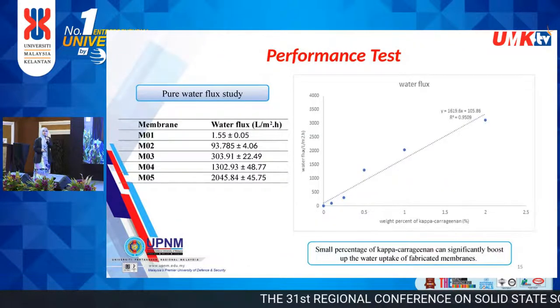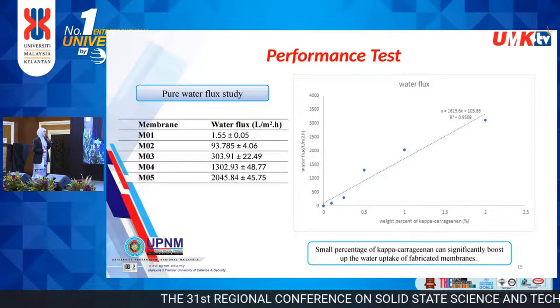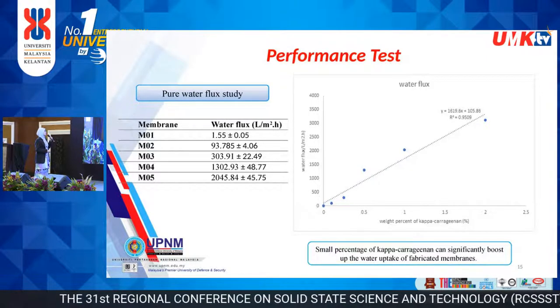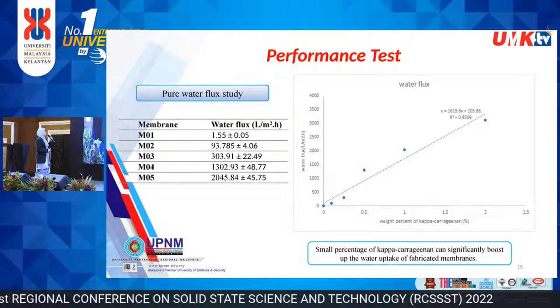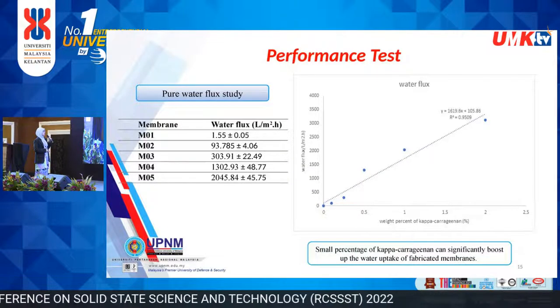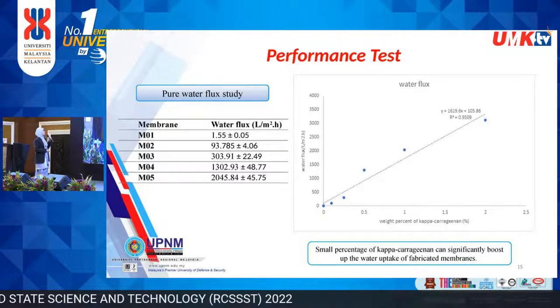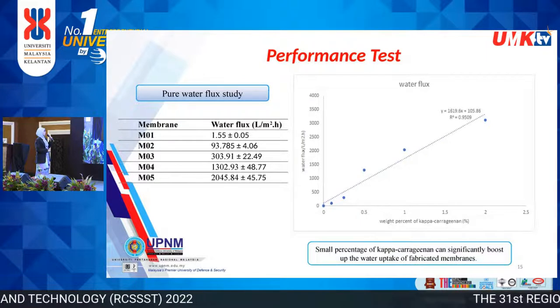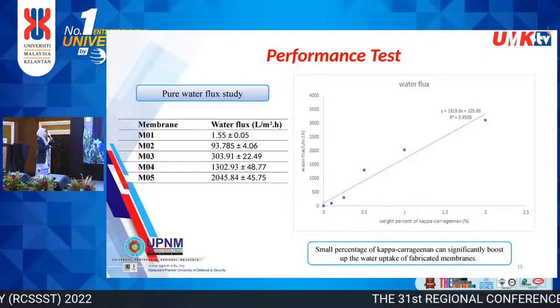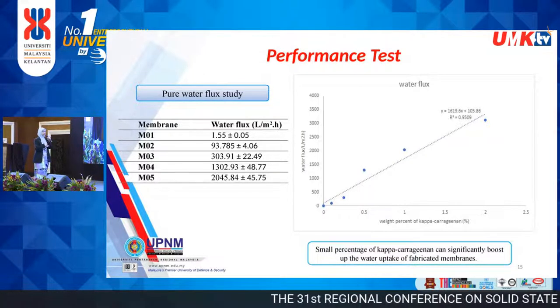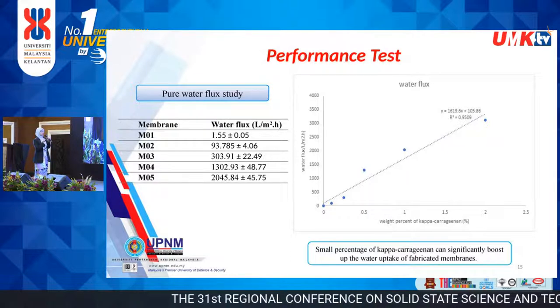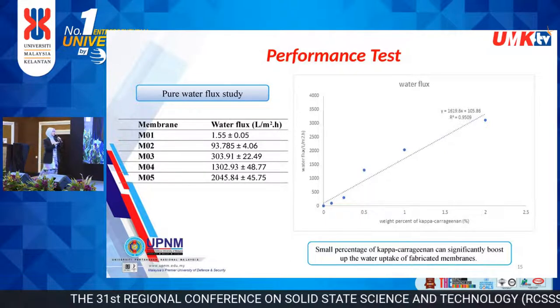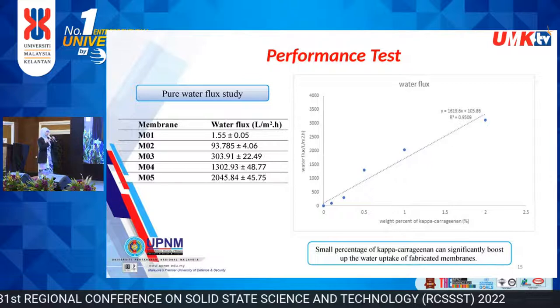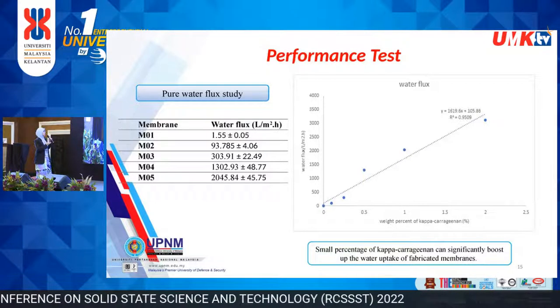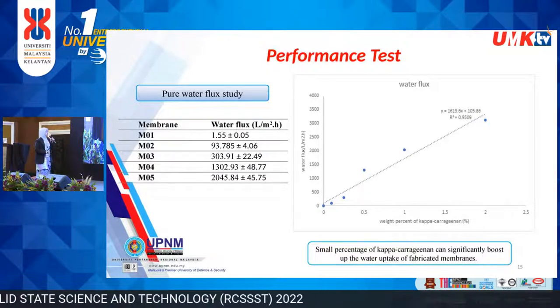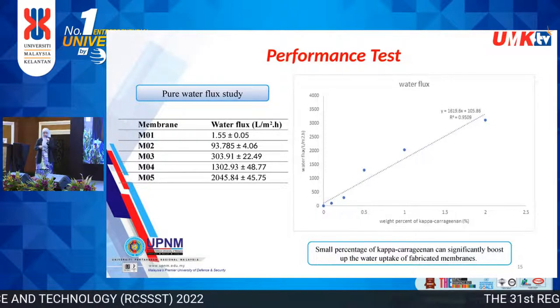All right. On the performance test, we check the pure water flux. As we can see here, of course the water flux is increasing. In comparison to pure polysulfone, M01, the water flux is very low. By adding a small amount of kappa carrageenan, the water uptake of the fabricated membrane significantly increases.